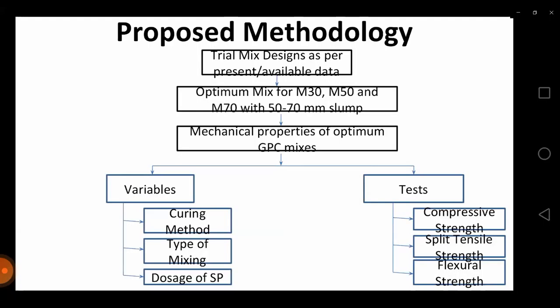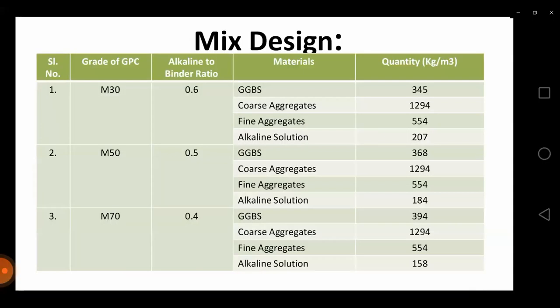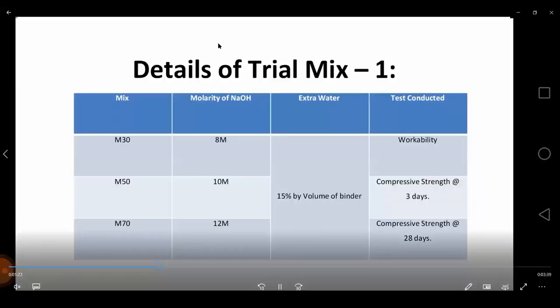And when it comes to the proposed methodology, we did so many trial mixes, and after that we got the optimum mixes for M30, M50 and M70. And we conducted the mechanical properties tests on these optimum mixes by considering different variables. And this is the mix design for different grades as per the previous literature and the trial mixes. And I carried out two trial mixes.